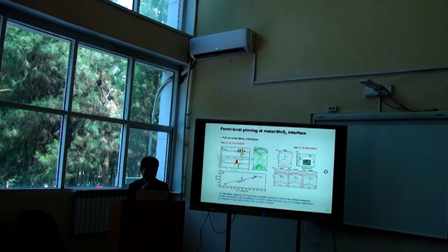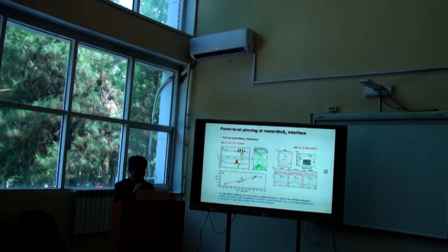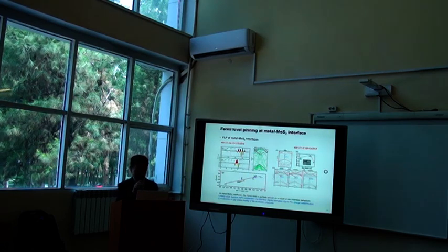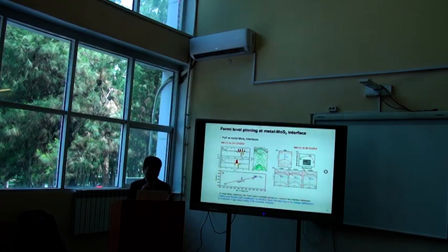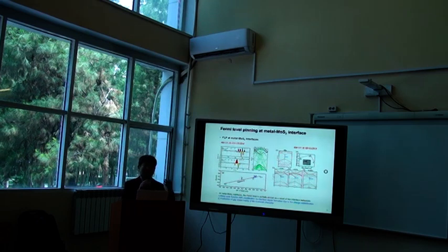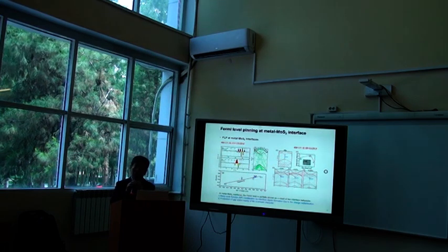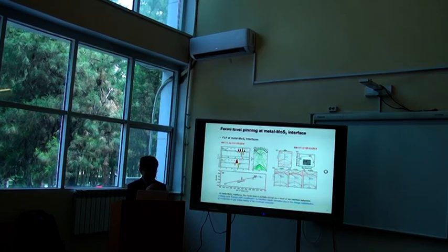A previous study by another group explained why this Fermi-level pinning occurs, and they mentioned two reasons. One is metal work function modification due to charge distribution at the interfaces, and the other is the production of gap states mainly due to the presence of orbital characters.